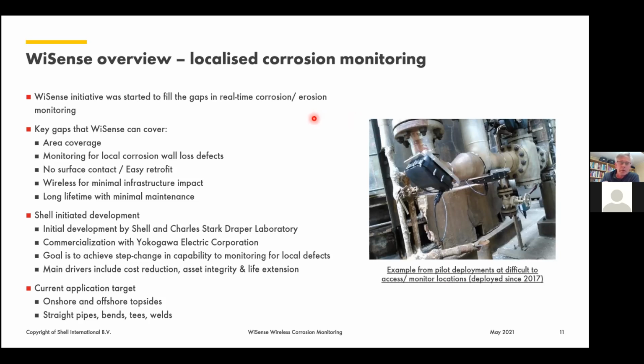So then to the left: the gaps in real-time corrosion monitoring, how did we try to cover that? Providing area coverage. Compare with, for instance, ultrasonics. If you would like to place an ultrasonic probe for monitoring on a local defect, you need to be pretty sure where the defect is. Otherwise, you might be either next to it or on the edge of it and getting a very unreliable signal from the depths of the defect. So you need to be spot on, on top of it. And although ultrasonics is a technique that provides us with the highest measurement accuracy in terms of depth, it is not easy to make ultrasonic arrays work on local defects. So the WiSense patch is providing area coverage, picks up local defects, wall loss.